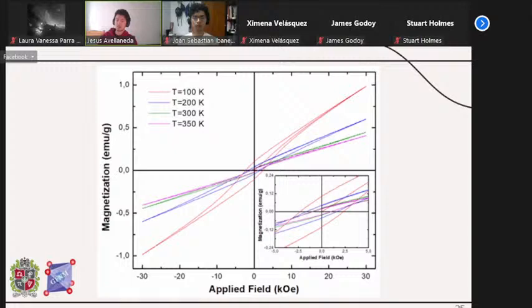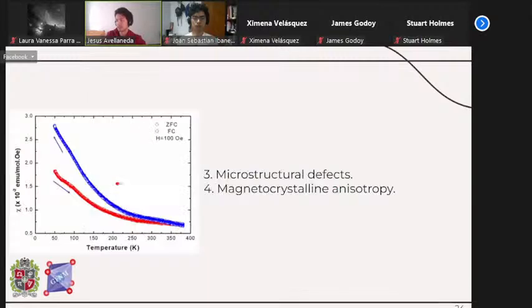Different isotherm curves are shown right here on the screen in a range from 50 to 350 Kelvin. We can see that the material in the entire temperature range studied presents a ferromagnetic response. Obviously, it is expected that in the range from 300 Kelvin and above, the ferromagnetic response, as you can see in these two last curves, decreases significantly. But it was curious, striking. I don't know a correct adjective to describe that, but it struck us a bit to see that it maintained its ferromagnetic character. Something that we can say with certainty, but we cannot give an exact value due to the limit taken. As you can see in the ZFC and FC curves shown before, there is no cutoff point where a clear intersection between both curves is seen.